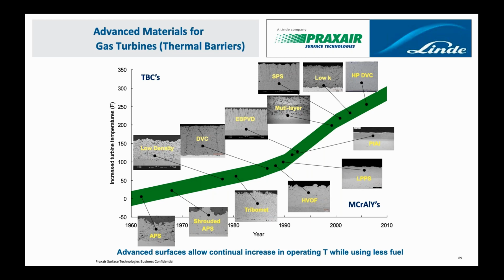And then as engine temperatures continue to increase, they needed further protection, say in the 80s and 90s, with something we call TBCs or thermal barrier coatings. All these micrographs on top are primarily yttria stabilized zirconia, but using different processes and different means to put these down to make either a porous or dense or dense vertically cracked coating for strain tolerance. So the newer state-of-the-art would be EBPVD, electron beam physical vapor deposition. Now you go from a horizontal splat structure to a vertical one, which gives you some strain tolerance, which just means longer life. It doesn't necessarily mean a better thermal barrier. It just means it's there and you can count on it and use it in your design in a more robust manner. And then further options.